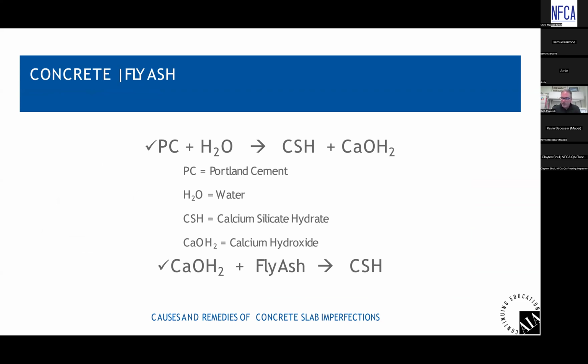Number one, it's considered a green material because we're using a byproduct in another product. But from a pure chemistry standpoint, you have Portland cement and water in concrete. Those two react together to create the binder that binds the sand and the stone in concrete. Chemically, that Portland reacting with water creates a material, the main binder in concrete, that's called calcium silicate hydrate. If you would chemically analyze concrete, the binder, the paste that's holding all that stone and sand together is calcium silicate hydrate. The byproduct of that chemistry of the water and the cement reactant produces a material in concrete called calcium hydroxide, or like free lime in concrete.